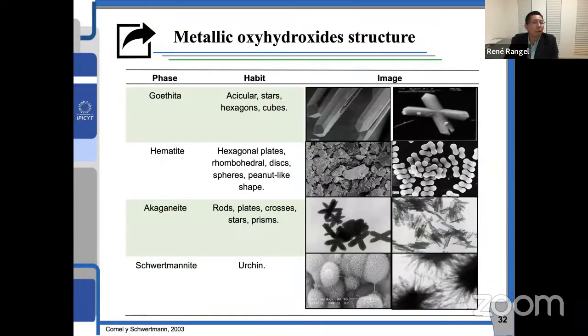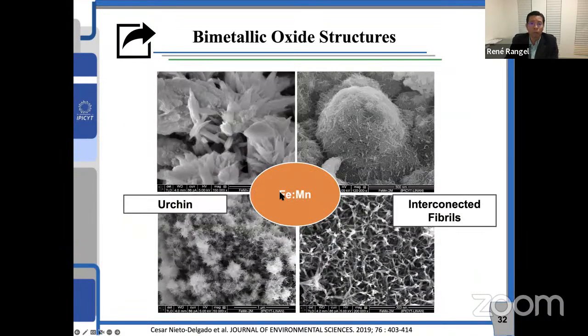Applying these mixes of metals, we have obtained different shapes of metal oxides. As you can see here, we have obtained this kind of stars. We have obtained also peanut-like shapes, this kind of plates and prisms, and others also. And recently, when we mix iron with manganese, for example, we obtain interconnected fibrils with also very high sorption capacity. As you can see, these materials are quite small and very amorphous. So it gives you very high surface area and very interesting sorption capacity. We have published also these results.